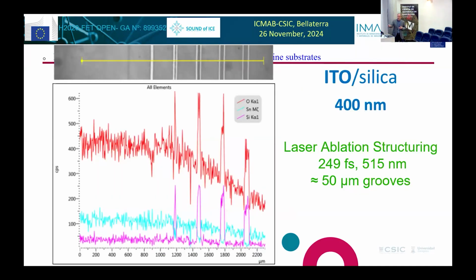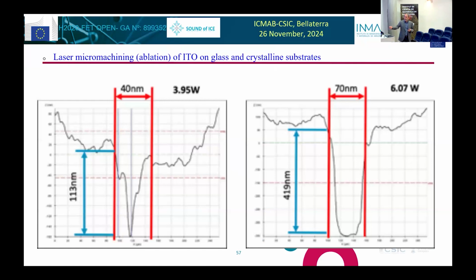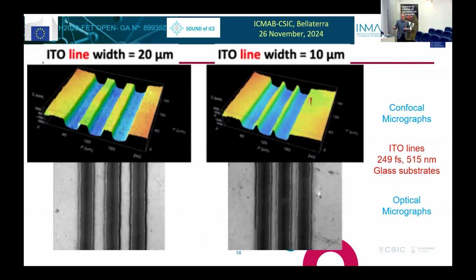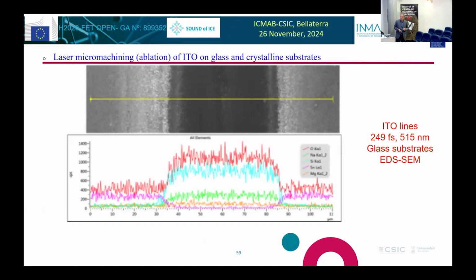So we do that, and we are able to machine the ITO, go down to the silica without damaging. We can see it, and usually you can engineer it to make it in different widths and different depths. You need to ensure that you go to the substrate in this case because you don't want an electrical connection. You want a very nice circuit. And so you can get very nice lines in the ITO, and you can measure at the microscope with EDS. You can see when you have the tin and when you don't have it, so you can really see if you have any remaining ITO layer.